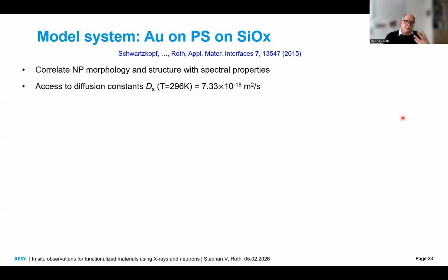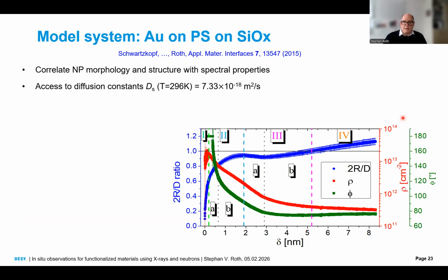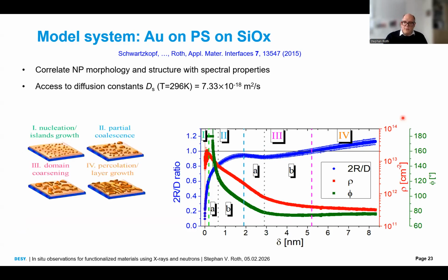We wanted to correlate the nanocluster layer morphology with its optical spectra. And first of all, what we can do is tell you all the details about the nanoclusters. Here you see the deposited thickness. Here you see the 2R/D ratio, meaning diameter divided by distance. In the beginning, you have many small clusters far apart, 2R/D very small. This increases because the clusters grow and grow and grow. You follow the blue curve.